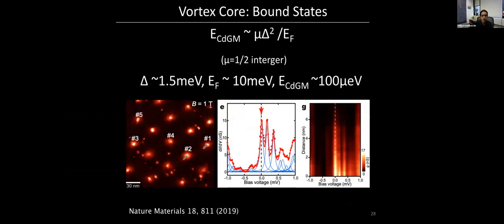So this is work done by Hanaguri's group. This is really beautiful, detailed work, and he shows many things quite clearly. One of the things he could do, because he could go to really low temperatures, is show that there are zero bias bound states where the energy resolution is good enough to say that these are well within this 100 microvolts. In fact, they're probably exactly centered at the Fermi energy. So that's pretty good proof that these are Majorana bound states.